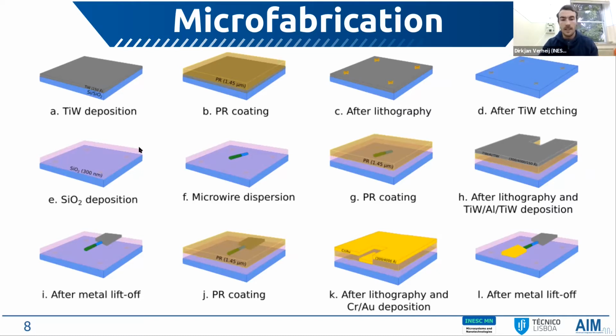And then we do a SiO2 deposition to isolate the substrate from the microwires, which are then deposited on the silicon oxide. And then we do two more photolithography steps, followed by metal depositions to create the contacts at the extremity of the wires. And we do two because we want different contacts at the P and at the N gallium nitride extremities in order to obtain ohmic contacts.